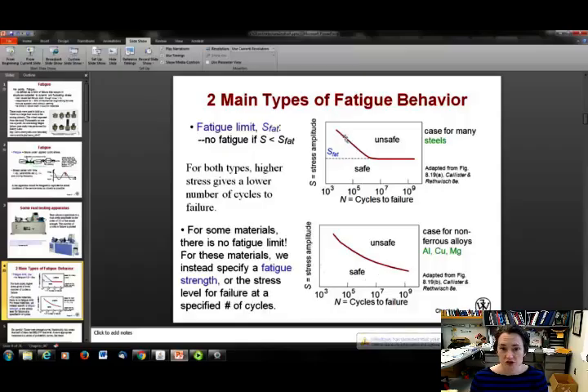So for these two different scenarios here, well, for both of them actually, higher stress is going to give a lower number of cycles to failure. That's why the curve goes up as it approaches low numbers of cycles. It goes up there with your stress amplitude, okay? So the part will fail at a lower number of cycles if you subject it to a higher stress. Not really surprising there.